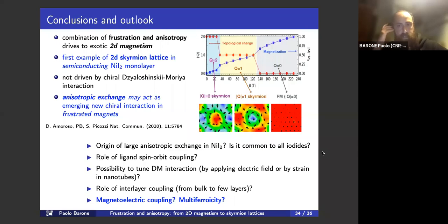One thing, for instance, is to understand the origin of such a large anisotropic exchange in nickel iodide, and to see if it is common to other systems also, not only iodine. And for this, it's probably important to take into account the role of the atomic spin-orbit coupling of the ligand. The other thing that could be interesting to check in this kind of system is to explore the possibility to tune the Dzyaloshinskii-Moriya interaction. In the pristine monolayer it's absent because of symmetry, but one can think of breaking such symmetry in some way by applying an electric field, or even more interestingly, probably by applying strain in nanotubes, so curving the monolayer to remove the symmetry constraint of the Dzyaloshinskii-Moriya interaction, which could be probably even larger than the anisotropic exchange.